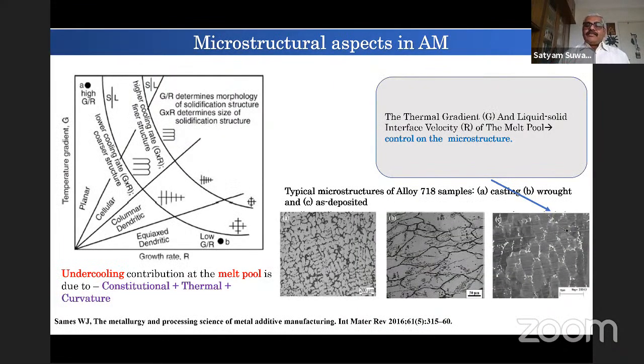Most important for material scientists in additive manufacturing is microstructural control. We can see that in Inconel 718, which is such an age-old material, used for almost 50 years in aero engines, there are subtle microstructural differences between the conventional cast, wrought, and additively manufactured material. As clearly mentioned in Professor Kim's talk, segregations are very common features of additively manufactured materials, and these segregations also lead to some amount of precipitate instability, and all these things have to be handled. Plus, the proper general microstructural morphology has to be addressed.